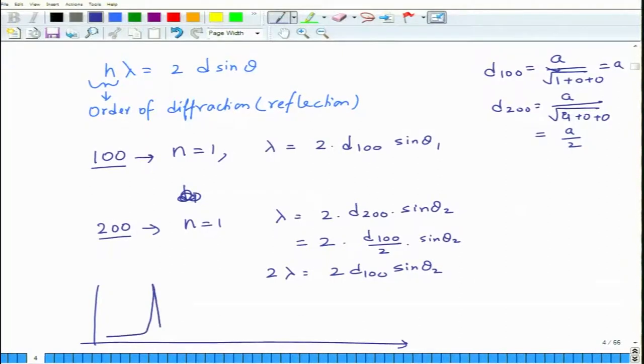So, when you have these diffraction peaks, you will have diffraction peaks in modern machines like these. So on and so forth. This is intensity, this is 2 theta. So, let us say if this is 100, I am not drawing other peaks, this will be 200, this is 300, this is 400. You can call this as first order 100, this as first order 200, this as first order 300. This has first order 400, or alternatively you can say this is first order 100, this is second order 100, this is third order 100, and this is fourth order 100. That is the significance of n.